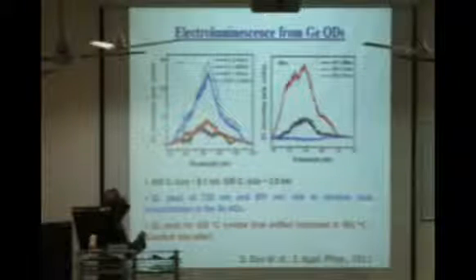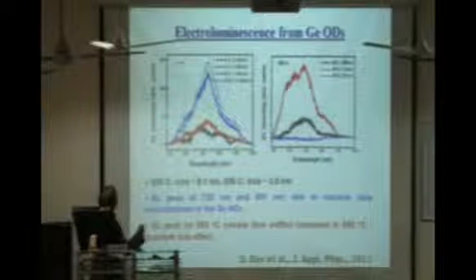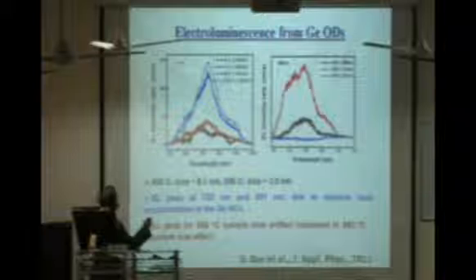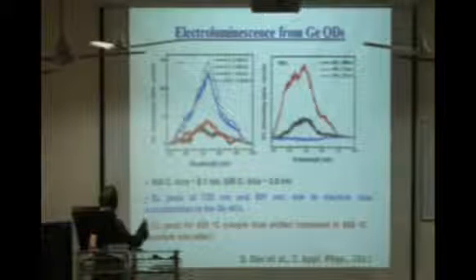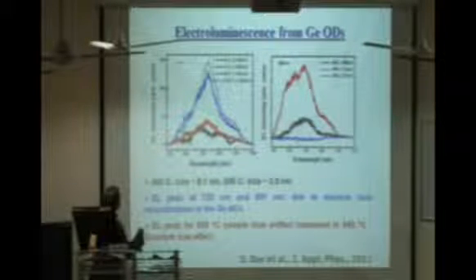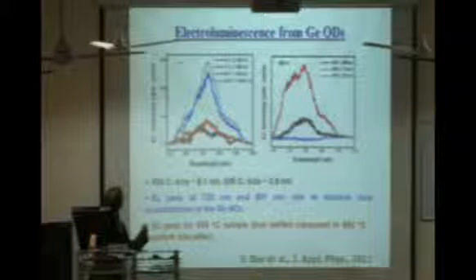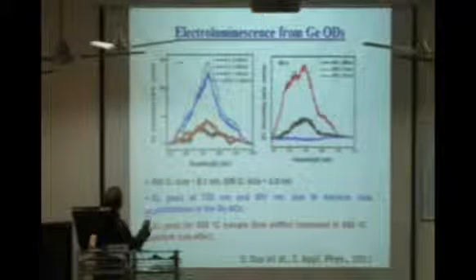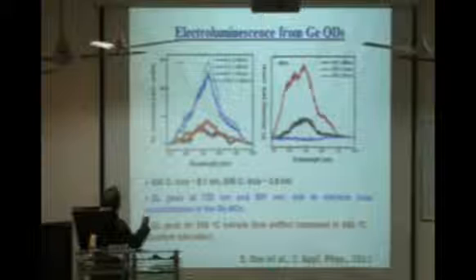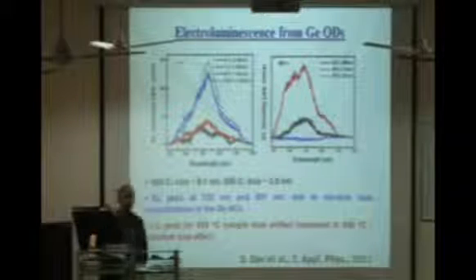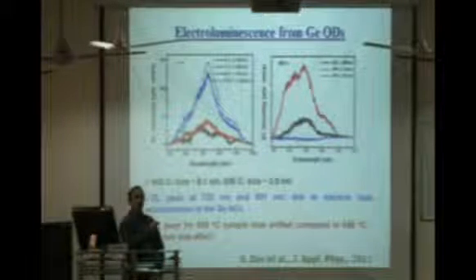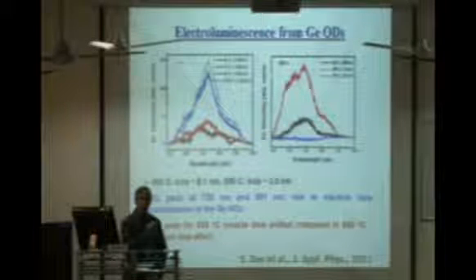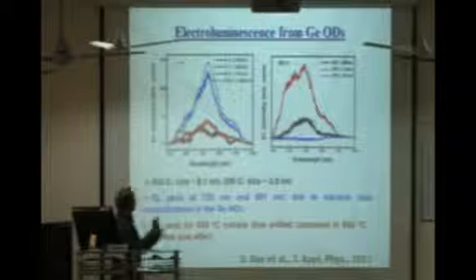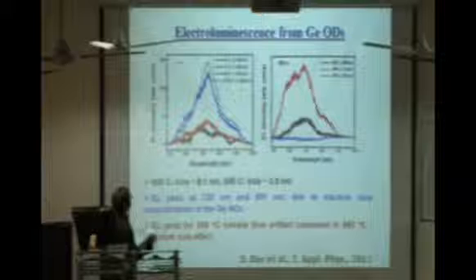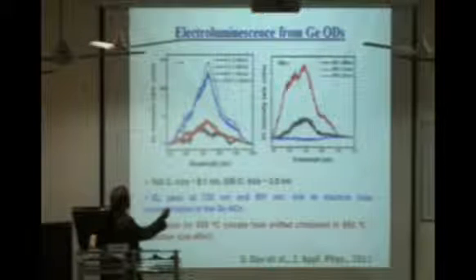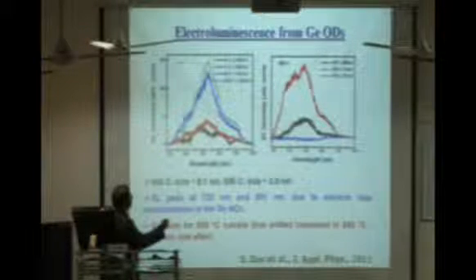And of course we get a very nice emission, as you see, in these two different samples I am showing. This is a better sample. Typically you start getting emission up to 6 volt, and as you increase the bias voltage, the emission intensity, or electroluminescence intensity, goes up. So here you don't have to excite the quantum dot with a laser. This is an electrically operable device. And forget about this, this is a different sample with a little bit more defects.